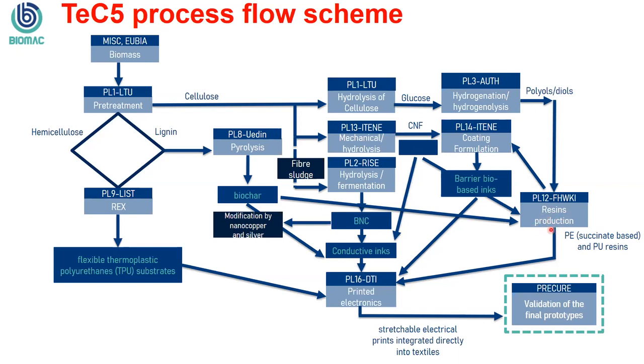Here it's a similar approach, but again, we're not using UV, we're using basically a heat cured system, but nonetheless reactive systems that are based on bio-based polyesters. And then of course we have all of our additives, various different kinds of additives. So you can see we can take the cellulose down this route, make nanofibrillated cellulose and use that in the inks. We can go this way and we have the bacterial nanocellulose coming in. These can also be used in our inks. We can use the lignin here to produce biochar. Maybe we need to modify it with a little bit of a metal coating to enhance the conductivity. Maybe not, it depends on the exact role of the ink.